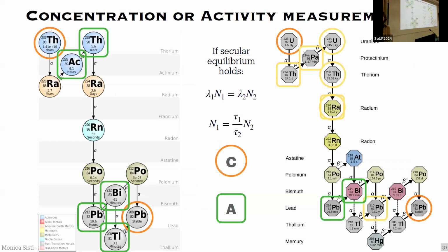On the previous slide, I didn't quite follow why the ones are in yellow? The ones in yellow are because it's more difficult to detect. If you go back to the slides where the branching ratio of the gamma decays is given, the branching ratio of these two decays is very small, so it's difficult to see the gamma line in the spectrum.